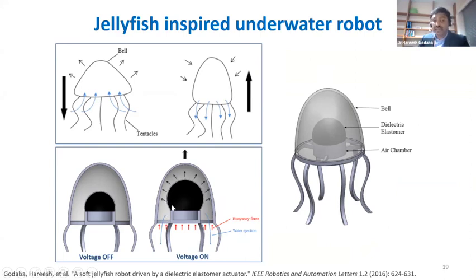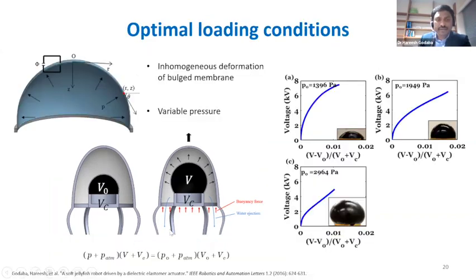It is quite reasonably fast actuation, less than 100 milliseconds, which can give us rapid movement of water from inside this bell. And also from some modeling, based on the mechanics of these elastomers and the PV gas law, what we found is that we have an optimal pressure that can help us achieve basically the largest buoyant force.